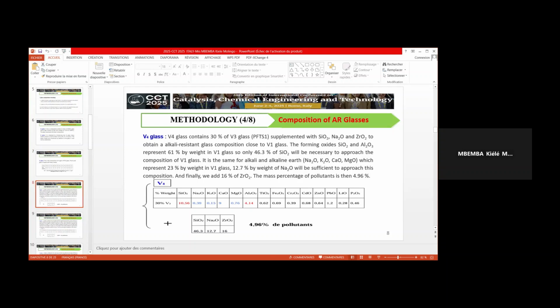V4 glass contains 30% of V3 glass supplemented with silicon oxide, sodium oxide, and zirconium oxide to obtain an alkali-resistant glass composition close to the V1 glass. So to get closer to V1 glass, we added 46.3% of silicon oxide, 12.7% of sodium oxide, and 16% of zirconium oxide. And the mass percentage of pollutant is then 4.96%.